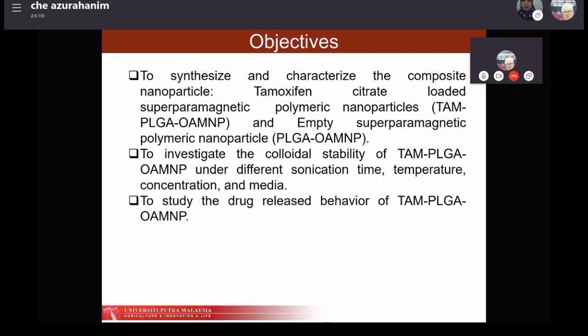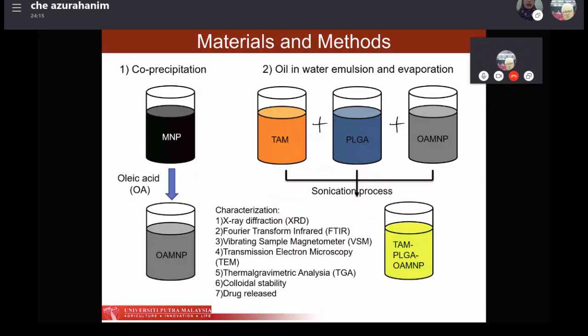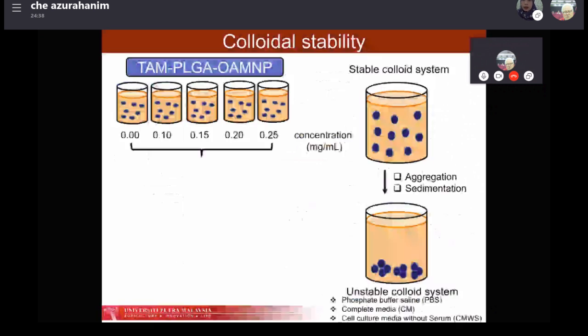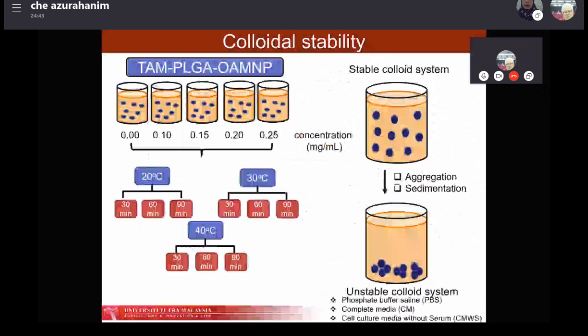So here are the materials and methods for her study. Very simple: we prepared magnetic nanoparticles using the co-precipitation method, and then we mixed with oleic acid. Then we prepared an oil-in-water emulsion and evaporation to prepare the TAM-PLGA-OAMNP. After we got the TAM-PLGA-OAMNP, we studied the colloidal stability. The colloidal stability is based on DLVO theory, Derjaguin, Landau, Verwey, Overbeek theory. That means a stable colloid system usually has less aggregation and less sedimentation, while an unstable colloid usually has aggregation as well as sedimentation. For this, she varied the sonication time, the temperature, as well as the culture media. We just tried the one with and without serum.